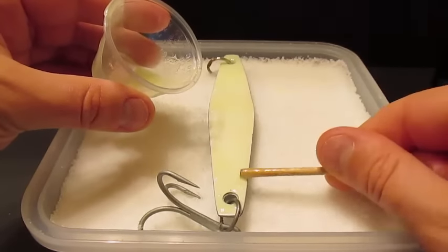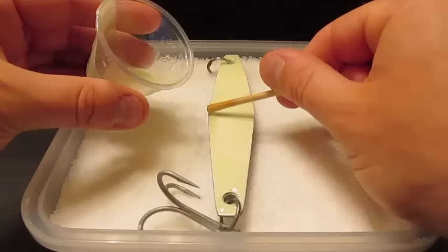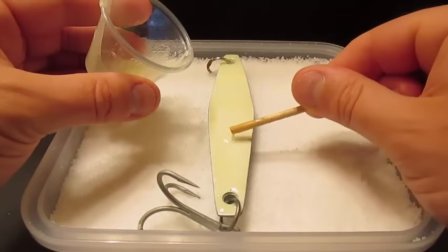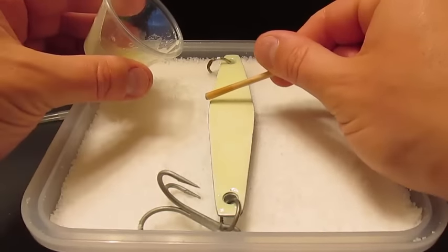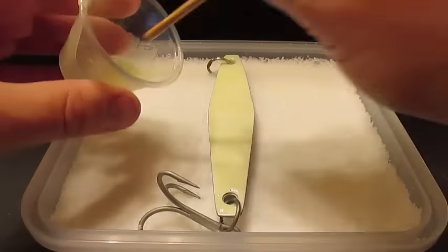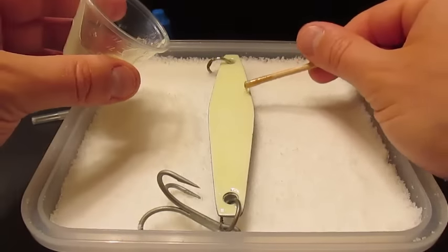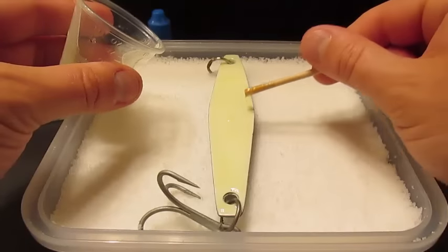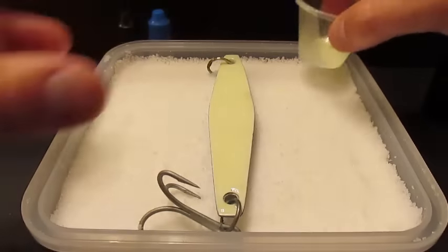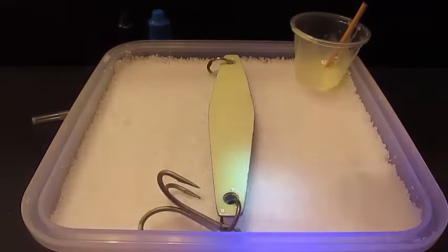Now, I charged this material that you saw glowing with a 365 nanometer UV flashlight that I got from Amazon for about $20. You can pick up other models between 375 and 400 nanometers for less, but higher wavelength UV LEDs can take longer to charge your jig, sometimes much longer. With a 365 nanometer flashlight, it will only take a few seconds.